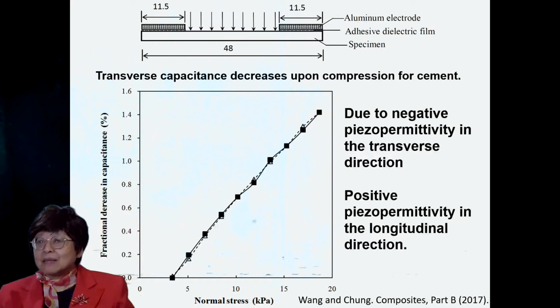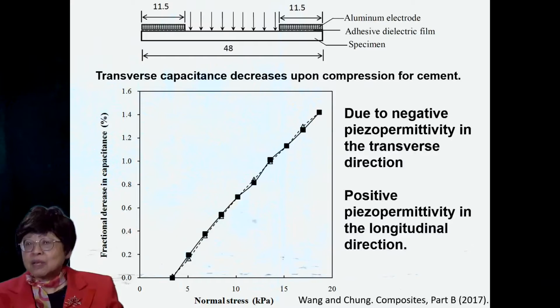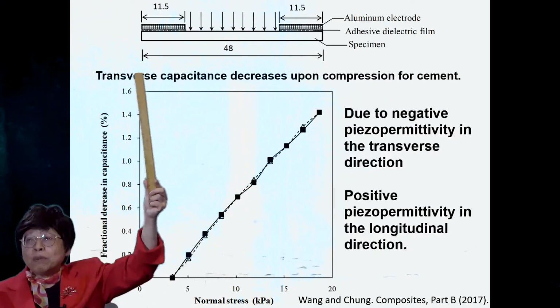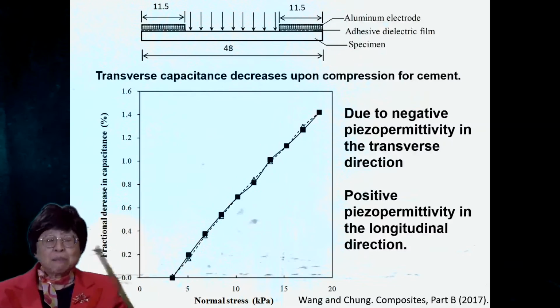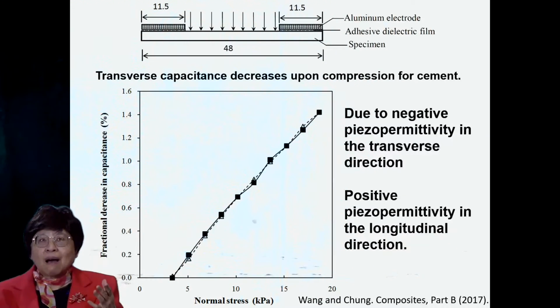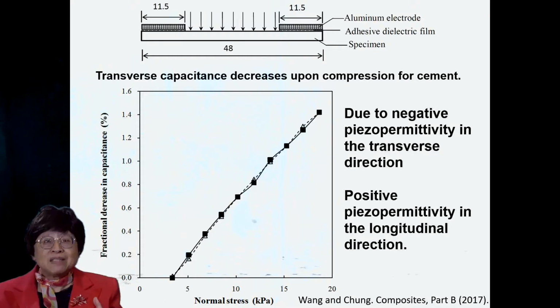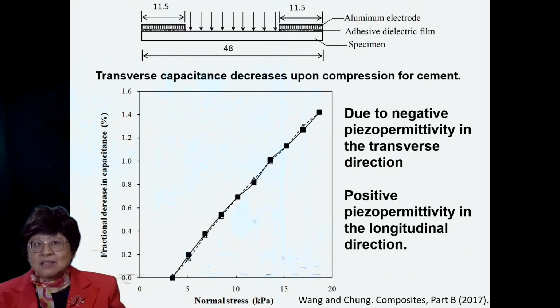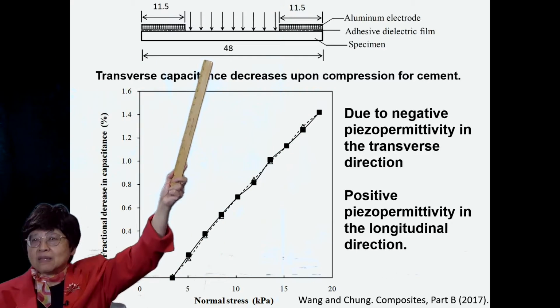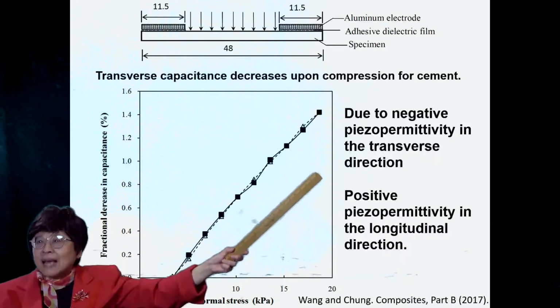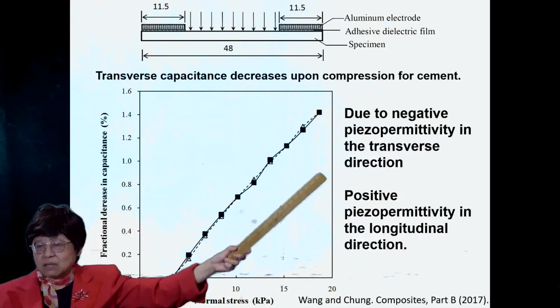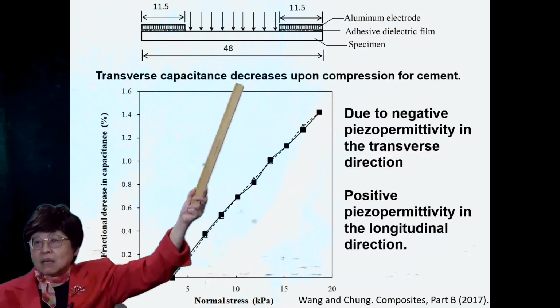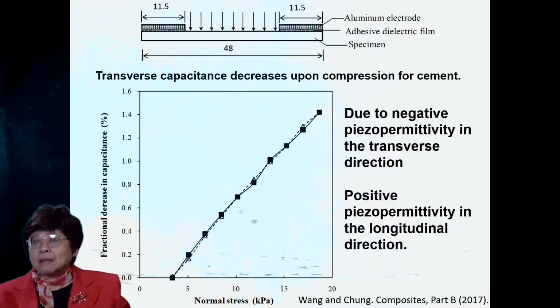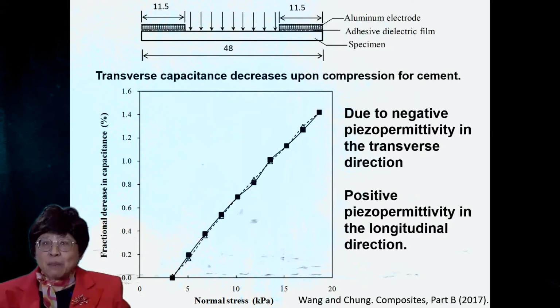For cement, the capacitance-based sensing also works. Here we use 2 coplanar electrodes and measure the in-plane capacitance because coplanar electrodes are more amenable to structural implementation for large structures than sandwiching electrodes. And the in-plane capacitance actually decreases upon the normal compression, and that's because of the negative piezo permittivity in this direction. But if one considers the longitudinal or vertical capacitance instead, one sees the capacitance increasing.